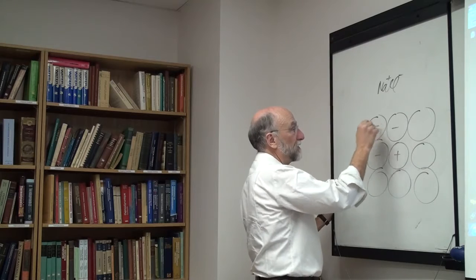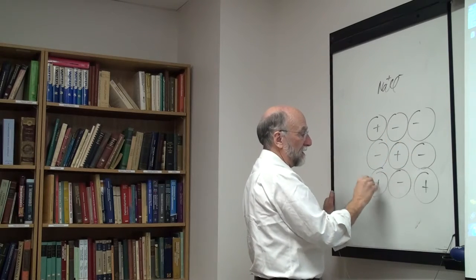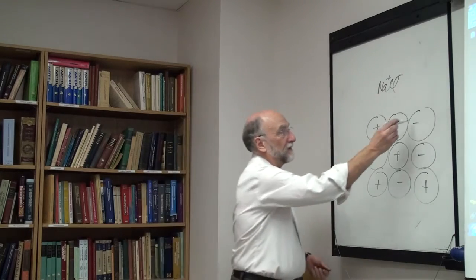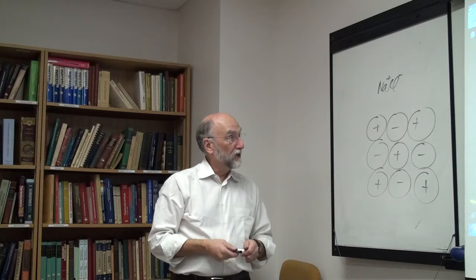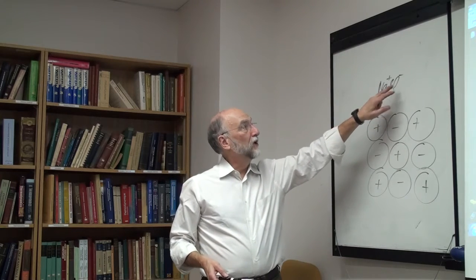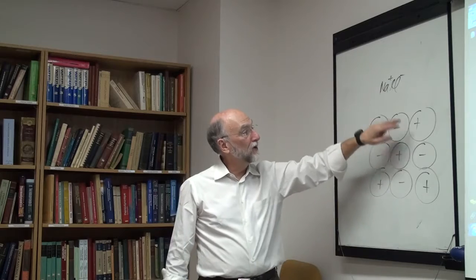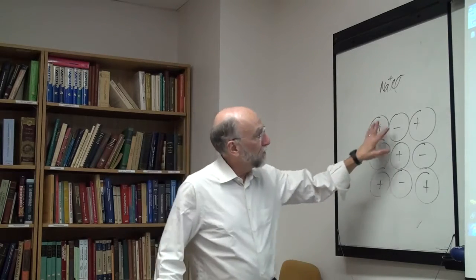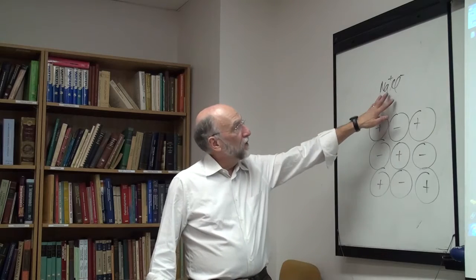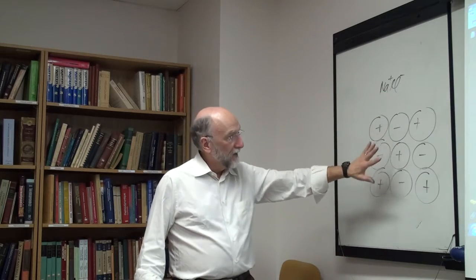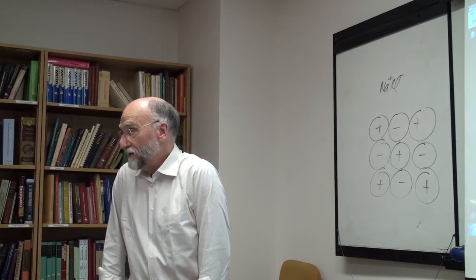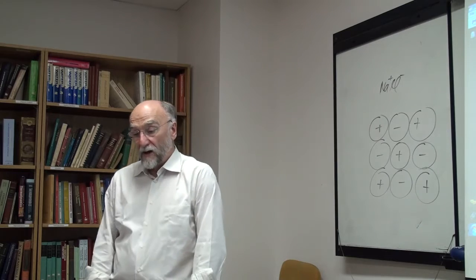You can have positive ions and negative ions. And although we know that as you go further and further away from the central ion, you have some possibility of substitutional disorder, it's so small. The probability that a chlorine is going to be on a sodium site and a sodium on a chlorine site is extremely small. You've got to get a long way away before you start to find disorder. So since we're only dealing with nearest neighbor forces, in modeling we can treat solid ionic salts as essentially being formed of two sublattices, even though in reality we know this isn't the case. And this is historically the way this was developed.